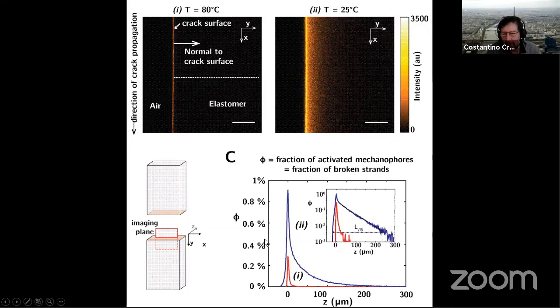And here on the left, you see the volume fraction, the number of mechanophore broken. So this is the concentration of broken mechanophore, which corresponds to the concentration of broken chains as a function of distance from the fracture plane. You can see that there is a pretty large difference between the 25 degree, which is the blue curve, and the 80 degree, which is the red curve. So very different in terms of bond scission.